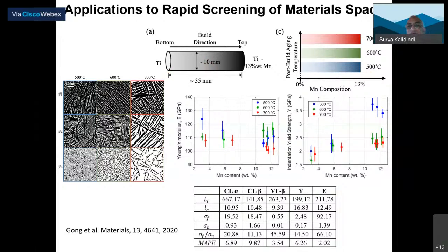Of course, we can do microstructure analysis and quantification to get various measures like chord length distributions, volume fractions, and other things. But most importantly, we can get the mechanical properties almost as fast as you can get the rest. In fact, the samples are the same samples. We do the microstructure, and after we get the microstructures, we are just indenting. So in some sense, the added cost is very little. And you can already see that some heat treatments are giving us much higher yield strengths than the other ones. So we can rapidly explore.